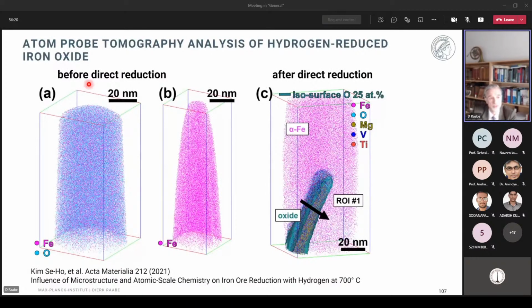And then, of course, here you see in the atom probe analysis, you have massive influence of the type of mineral that you use, because many have now, of course, gangue elements. They have chemical tramp elements that in part form very, very stable oxides that you simply don't reduce. And that is something we only started to study because this is a totally different game. In classical steelmaking, you inherit your impurities from the coke, from the blast furnace, while here you mainly inherit all your impurities that matter from the oxide.